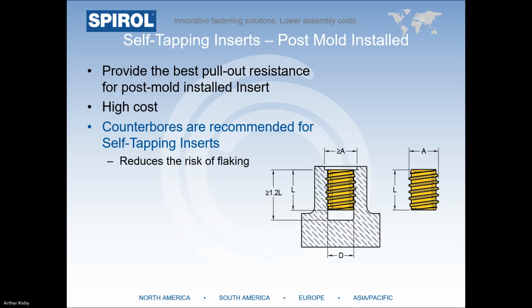Counterbores are typically not recommended for any insert except self-tapping or headed inserts. Counterbores are recommended for self-tapping inserts to reduce the risk of flaking. The outside diameter of the counterbore should be equal to or larger than the outside diameter of the self-tapping insert.